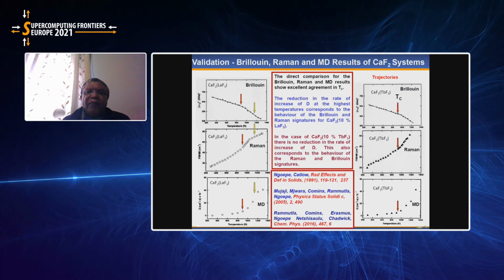Now, I'm just giving here an indication of some work that we did a long time ago, which is now re-imaging on fluorine ion conductors, which shows a very good correlation between experimental results like laser spectroscopy, Brillouin spectroscopy, Raman spectroscopy, and how those related to the molecular dynamic simulations that can be carried, and which show different types of defects, particularly in calcium fluorides that are doped with lanthanide fluoride, and those that are doped with terbium fluoride. The manner in which these elastic constants change show us where there is an onset of the superionic phase in the material, and we can see the differences in the manner in which these materials change.